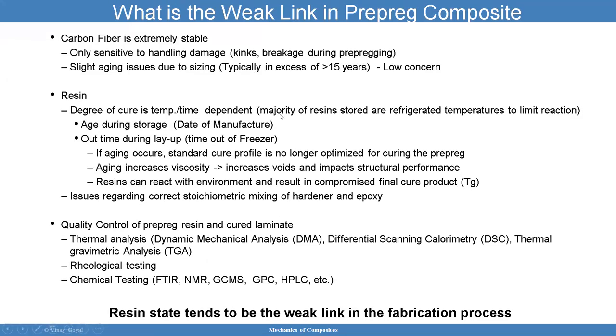So what is a weak link in pre-preg composite? The weak link is really not the carbon fiber. It's extremely stable. So that's not going to do it, but carbon fibers are sensitive to handling damage, kinks, breakage during pre-pregging. There's slight aging issues due to sizing, typically in excess of 15 years.